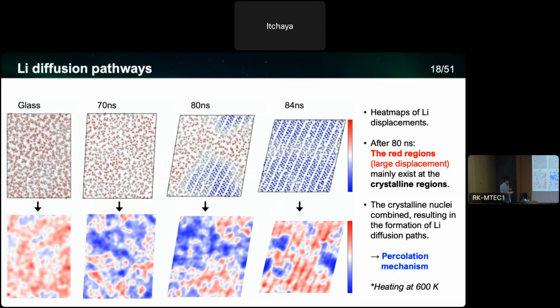So probably when we use different temperatures, the mechanism may be different, because the high temperature phases will be precipitated at this high temperature, but when the heat treatment is lower, like 400 or 500 Kelvin, that alpha phase may not appear, and a different mechanism will play a role. But in this simulation, what we found is like this.